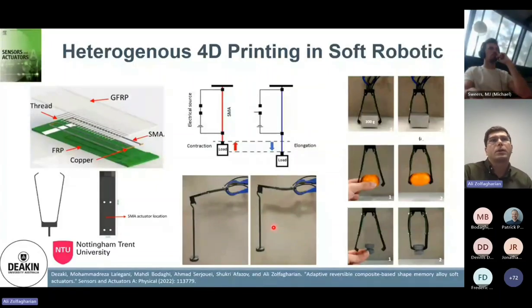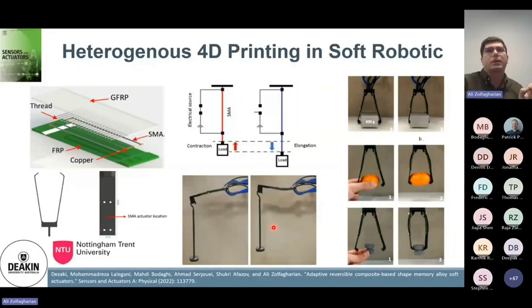And in another work, we came up with the idea of heterogeneous 4D printing. I saw this term earlier from another colleague, Frederick Demoli, whose talk you will see later after mine. I think he came up with this term earlier, and I like it, heterogeneous 4D printing. We use 3D printing for some parts of the robots, and then we use some actuators externally to add to that. In our sister lab at Nottingham Trent University, we developed this idea and added shape memory alloy, and then we used the 3D printing parameters for getting different stiffness, as you could see, different payloads, and different sizes that we could achieve with this sort of soft robotic application in 4D printing. Indeed, that is what we name heterogeneous 4D printing.